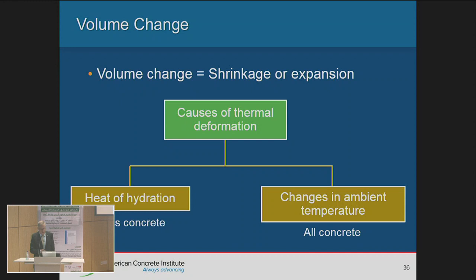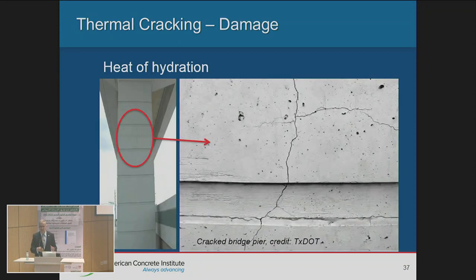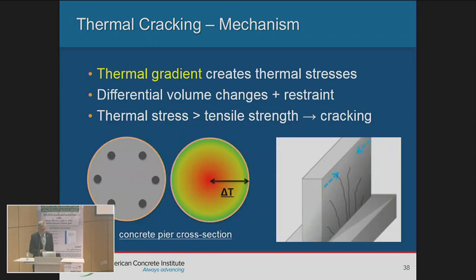We talk about volume change. We have heat of hydration and changes in ambient temperature. When we talk about heat of hydration, it's mainly mass concrete. And you see those cracks because, again, the inside of the concrete is still hot, whereas the outside, which is in contact with the environment, cools down, so the concrete cracks. And there are some requirements. There are ACI documents that talk about the requirements of limiting the high temperature and the difference between the external and internal temperature in concrete. And there are other methods to mitigate those cracks, as talked about here, with the thermal gradient.